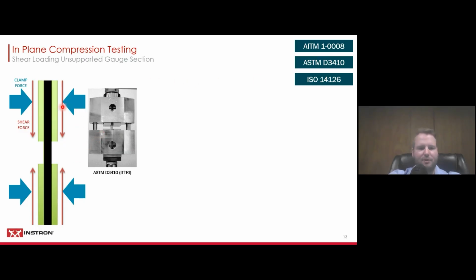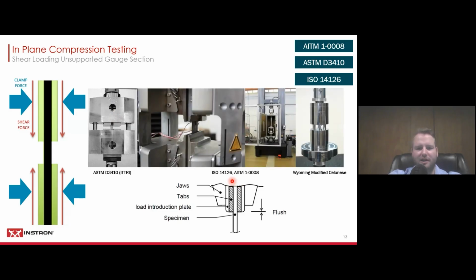So you're clamping on the sides, and then this gets driven together. So either you come down with a compression platen on the top of the fixture and compress it, or if you run it like the Airbus standard, for example, allows, hydraulic wedge grips that you use with load introduction plates in between your gripping and your specimen. So you clamp on the sides of the specimen and then drive the crosshead down, and then you initiate the compression like that. But it is through shear, not through the ends of the specimen. So this will also give you different results. They're not comparable to the end loading results.